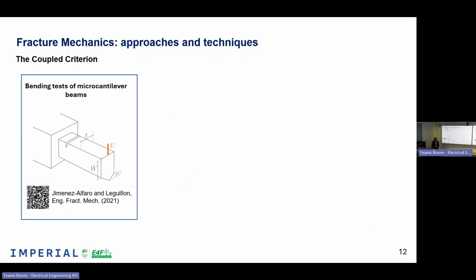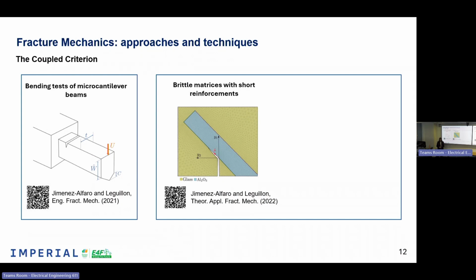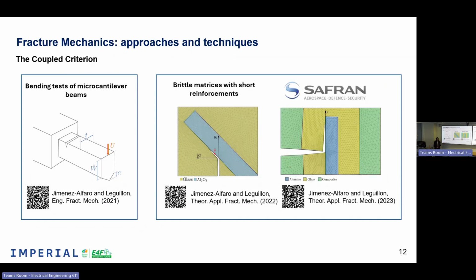So this theory has been applied in many fields and applications. For example, we have used this theory to predict the fracture toughness of ceramic materials in bending tests of microcantilever beams. We have also used this to predict crack jump, crack propagation, crack deviation of some brittle matrices with short reinforcements, such as platelets or short fibers. And in fact, we have also included the effect of volume fraction and residual stresses. This was very interesting work because this was an industrial collaboration with Safran. Safran is also very motivated to improve their engines because they need to arrive to the net zero gas emissions that we were talking about before. So they are trying to investigate new materials. And among others, one of these materials for their engines was very similar to this one. So we estimated for them the fracture toughness of their material for their new design.